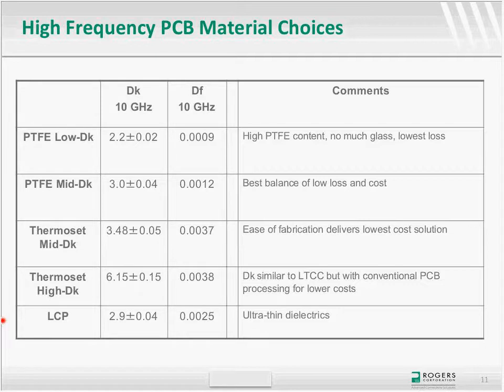So as you go thinner in dielectric, you will see bigger impact to the conductor loss. So at high enough frequencies, you do find that the conductor losses are a very, very significant portion. So that is what governs quite a bit, assuming that you do have a low loss system. If you don't have a low loss resin, then it's a different story. Then you can't have as much an impact on dielectric losses as you do on conductor losses.